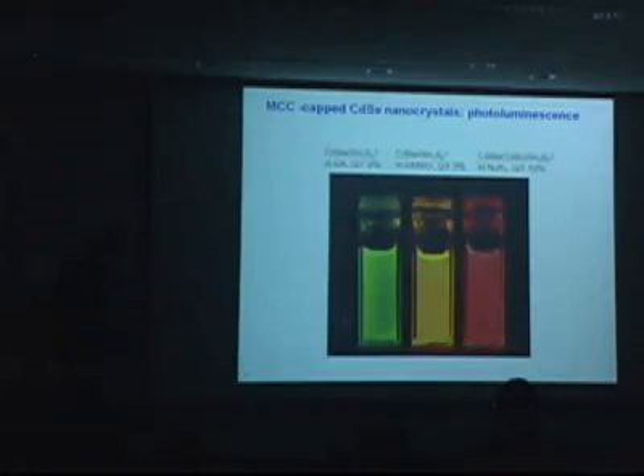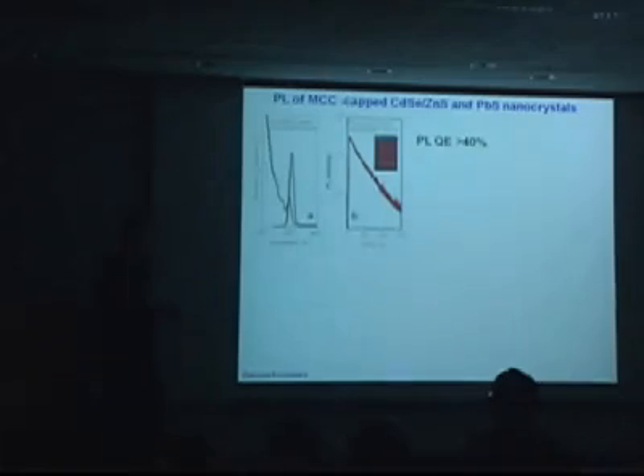Now, another important point, of course. Every time you put something at the nanoparticle surface, the question is what you do to the electronic structure. If you introduce mid-gap states, if you introduce charge trapping. And here it was pure luck for us that we found that these molecules do not harm electronic properties. We still have band gap, band edge, luminescence controlled by quantum confinement. We can form excitons, they do not quench, so we can make these bright samples.